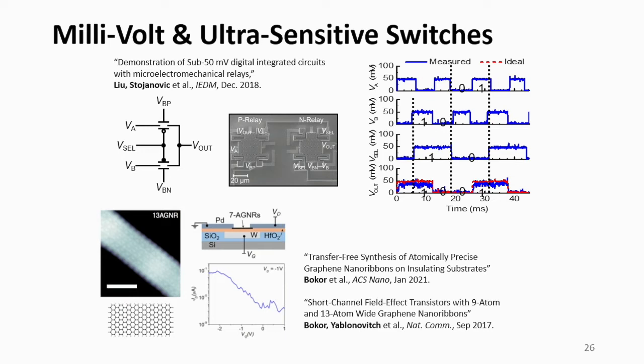Now, other types of very sensitive switches include graphene nanoribbon transistors. Now, the energy band gap of graphene depends very sensitively on the width of the graphene nanoribbon. And so my colleague, Professor Bokor and Professor Yablonovitch at Berkeley, have collaborated with people in chemistry to find ways to chemically synthesize graphene nanoribbons precisely, so they can control the width of a graphene nanoribbon to within less than an angstrom.